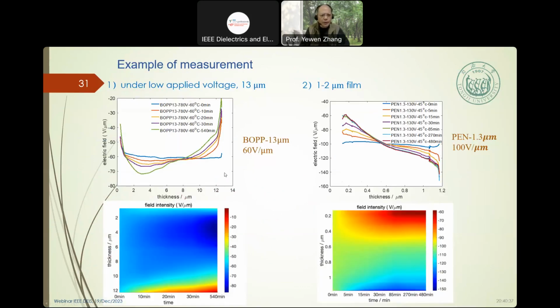So these are some measurement results under low applied voltage. For example, 780 volts for 13 micrometers. This one is 130 volts for 1.3 micrometers. So the field is also very high, but the sample is very thin. So we can get good resolution near the sample surface, about 0.05 micrometer. But it cannot be used for very thick samples. Over 20 micrometers is almost not possible.